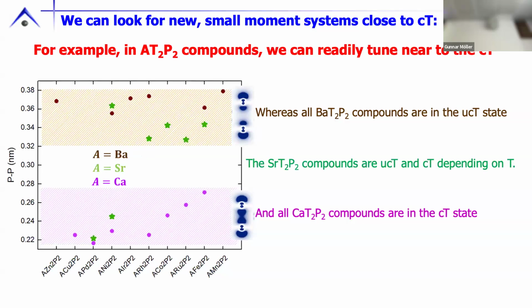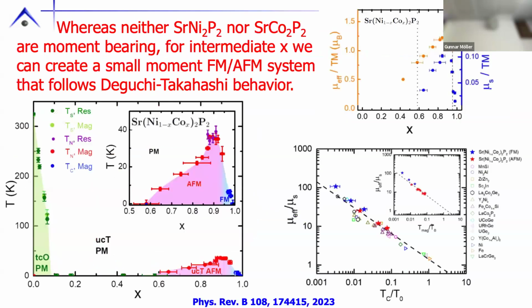All right. And if we look at strontium, we can see that strontium straddles. So strontium looks promising. As a matter of fact, strontium nickel 2 phosphorus 2 is really right on the edge. Neither strontium nickel 2 phosphorus 2 nor strontium cobalt 2 phosphorus 2 is moment bearing. They're not magnetic. On the other hand, if we dope in between them, we can see that as we get beyond about 50% cobalt, we can stabilize small moment antiferromagnetism. It rises, it falls, it changes to small moment ferromagnetism, and just before we get to cobalt, it becomes non-magnetic again.